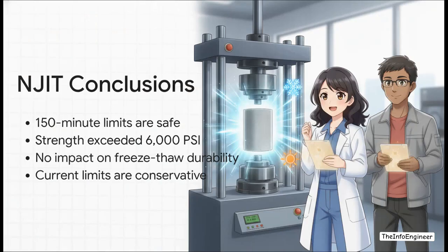The takeaway here is huge. The NJIT data proves definitively that the current 90-minute limits are actually highly conservative. The test cylinders they poured at 150 minutes still smashed right through their 6,000 psi compressive strength targets, and they showed zero negative impact on freeze-thaw durability. It just goes to show that with precise time-bound operational management and on-demand chemistry, we can safely extend that ticking clock, saving millions in wasted material and idle labor.